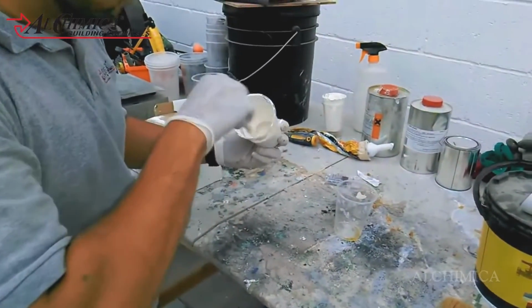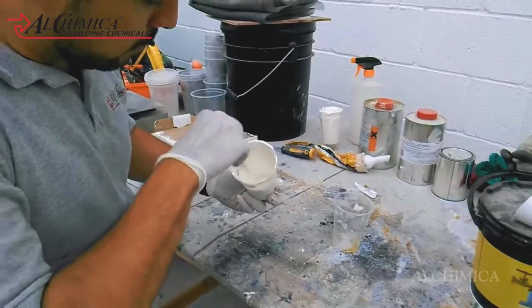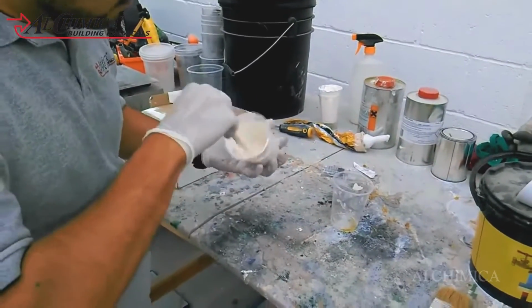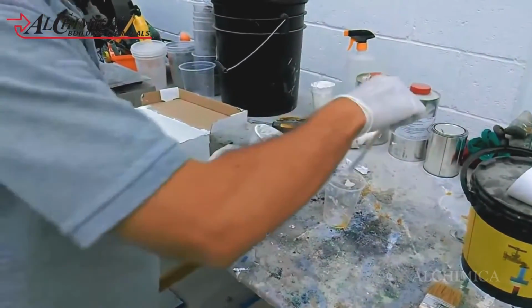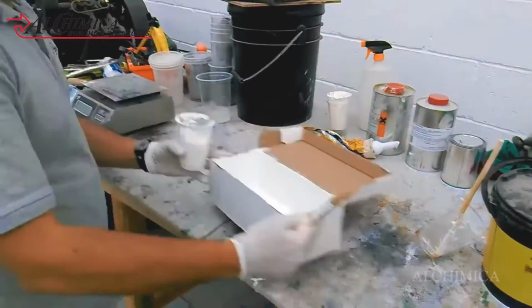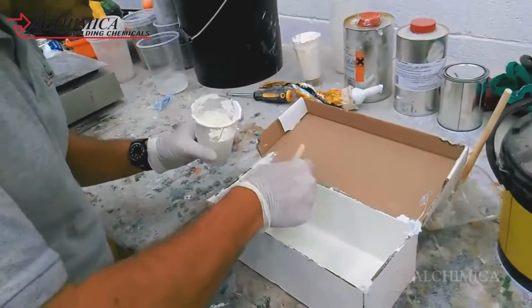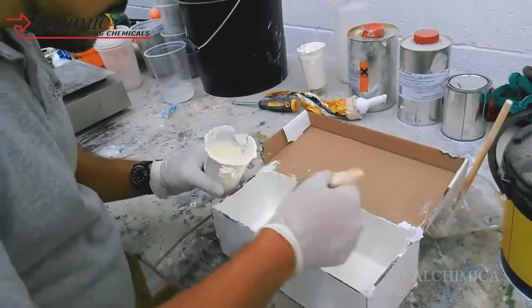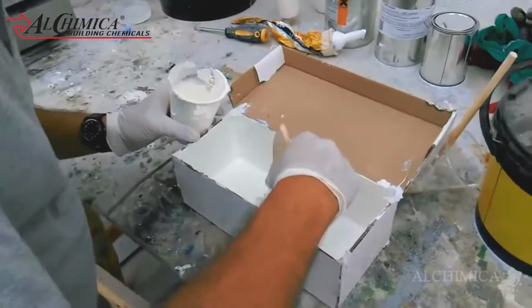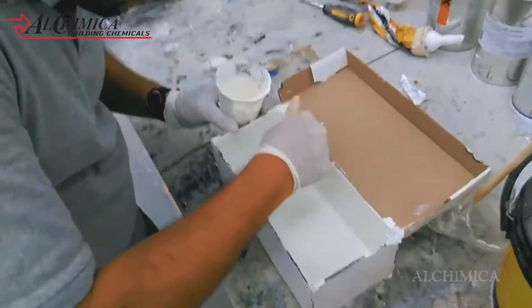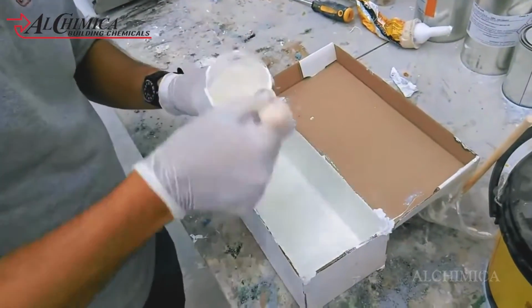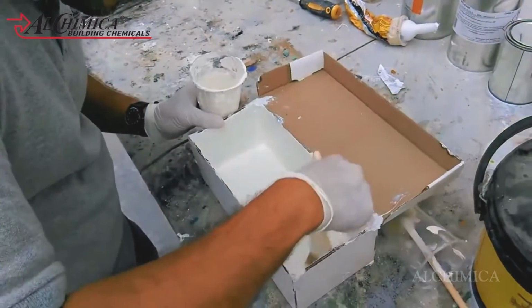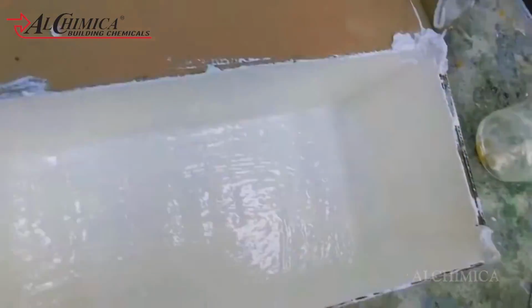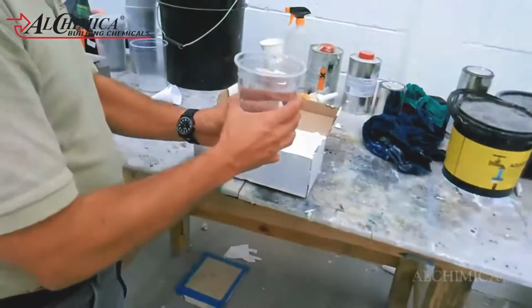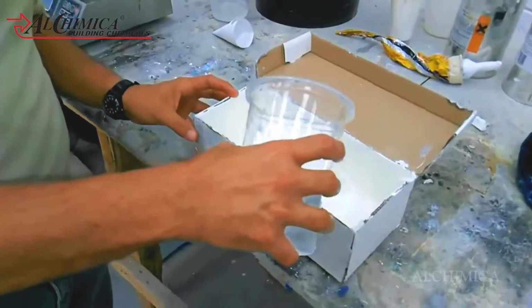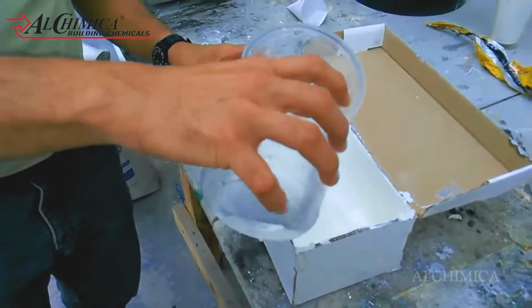The floor, or horizontal surface, coating can be carried out in a single coat at the rate of 1.4 kg per square meter if it is a closed water tank. The inner surface of the ceiling is coated with a single coat of Hyperdesmo 2KW at the rate of 0.7 kg per square meter. The cured membrane of Hyperdesmo 2KW has very high surface hardness, Shore D40, elongation 100%, tensile strength 20 MPa.